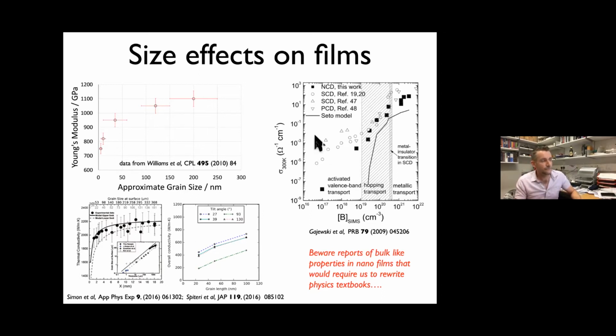My main point here is: just be very careful with reports of bulk properties in nanofilms, because this would require us to rewrite physics textbooks. If you really had a high mobility in a nanocrystalline material, that would mean that your mean free path is substantially bigger than the grain size. It isn't. Somebody made a mistake.